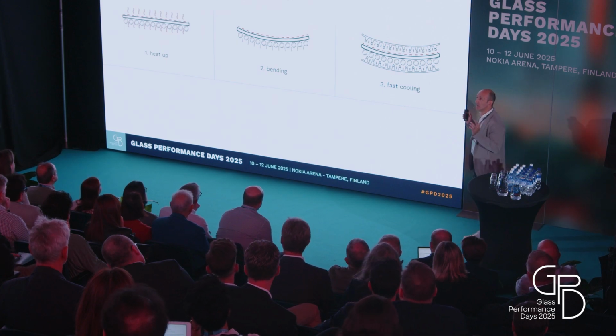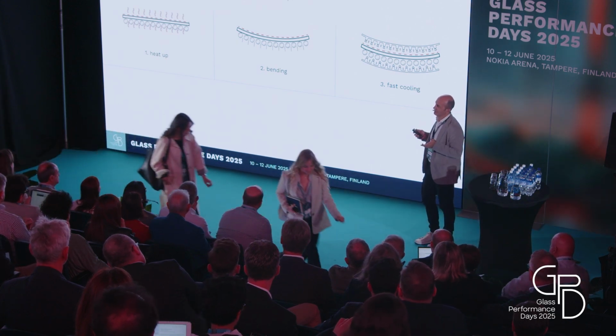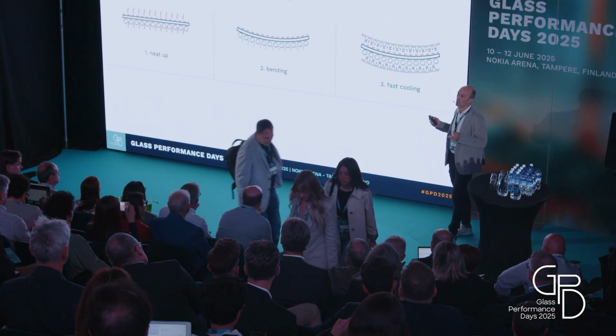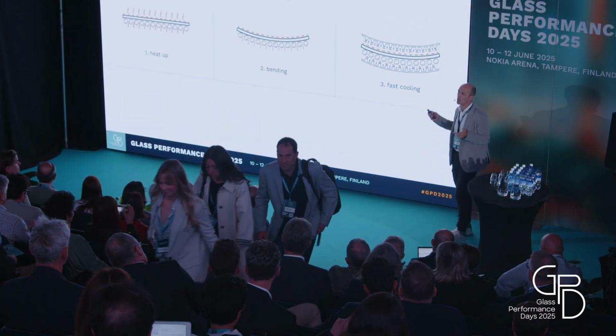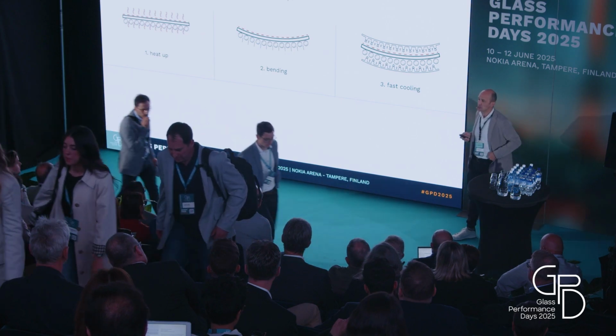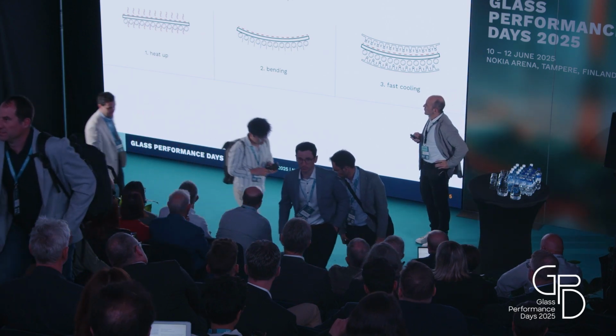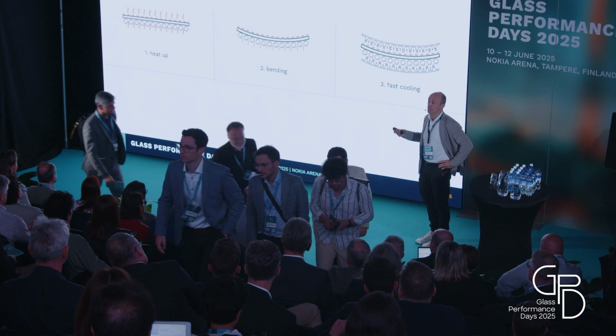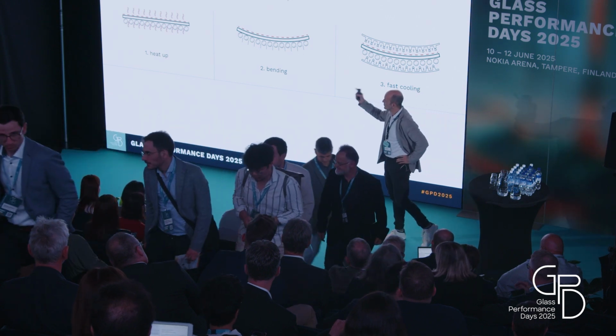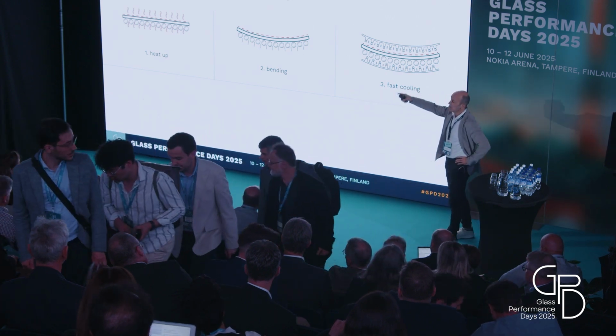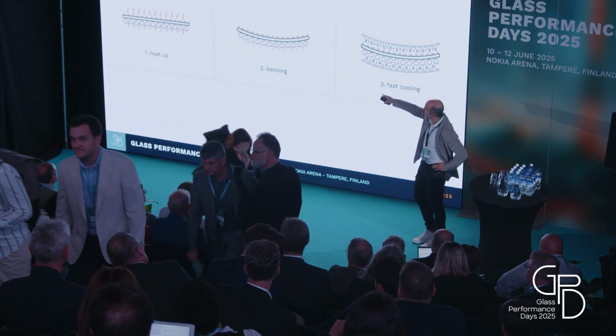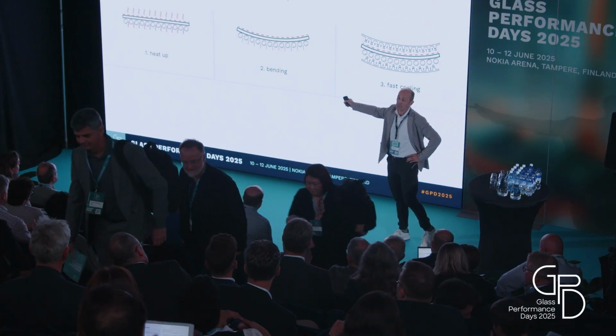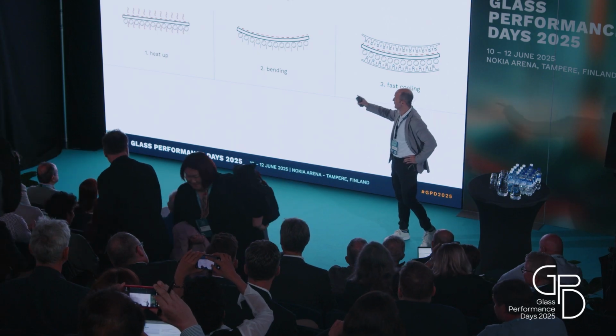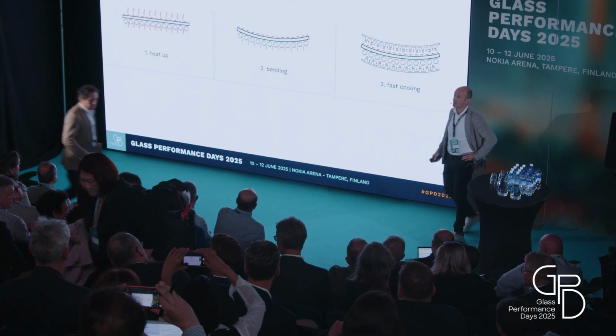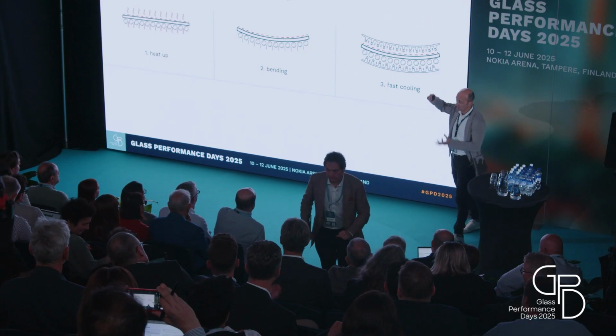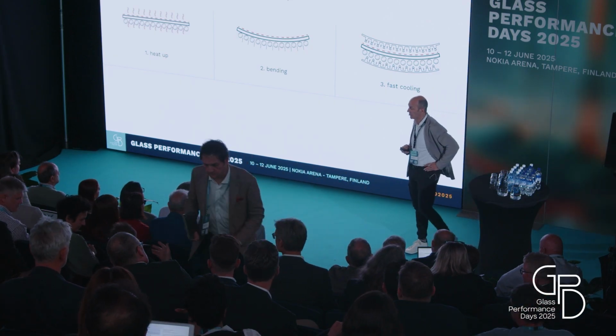When we think about glass for building in general, it's this. In general, it's what we call machine bending, thermal bending. So bending, toughening, bending, and heat strengthening. The process is known. It's a very fast process. Glass gets onto the rollers, keeps moving to avoid roller wave distortions, reaches the right transition temperature, moves to a second section. Glass is bent in 5 seconds, super fast, very fast production. And afterwards, basically, we cool down the glass. We quench the glass symmetrically so that the glass is properly toughened.